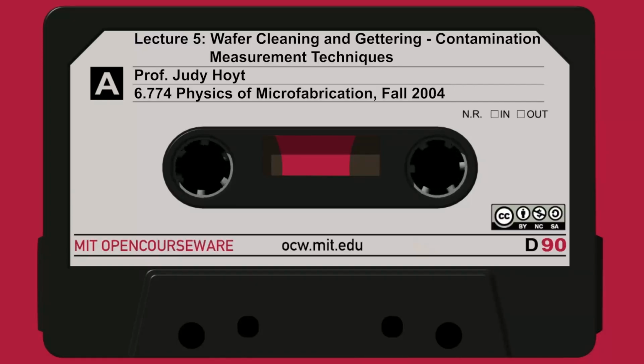Third type, QM. Mobile charge, well, as the name suggests, these ions are mobile. That is, they can move in the oxide from the top surface to the bottom interface. They can move up and down upon application of an electric field. They're ionized. So if you heat the oxide, say to 100, 200, 300 degrees, and you put an electric field on it, you can actually cause these sodium and potassium ions to move from here to here and back.